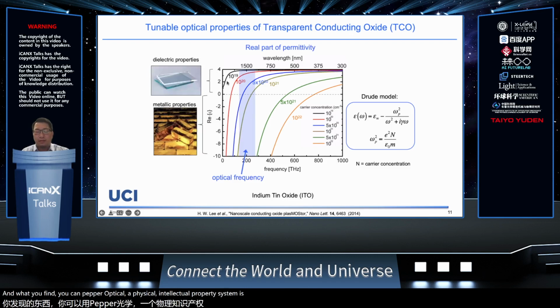That means a positive permittivity, or a negative permittivity, which means a metallic property, depending on the carrier concentration of the material. So that means it's really good. By changing the material property, you can change the optical property of this material, and we can change it quite significantly. There are different ways to do it.